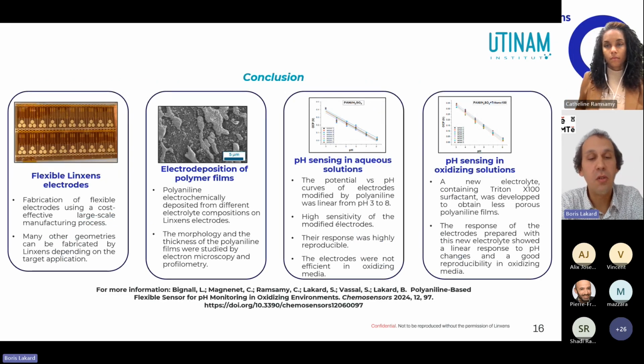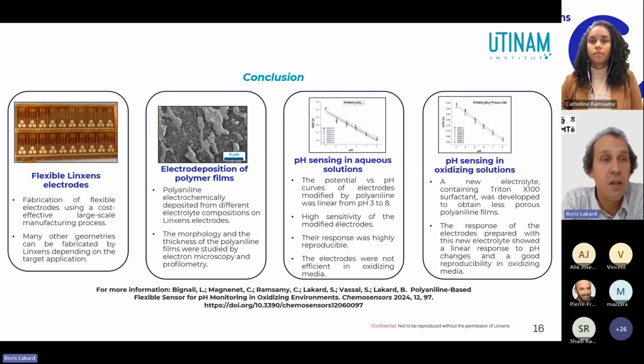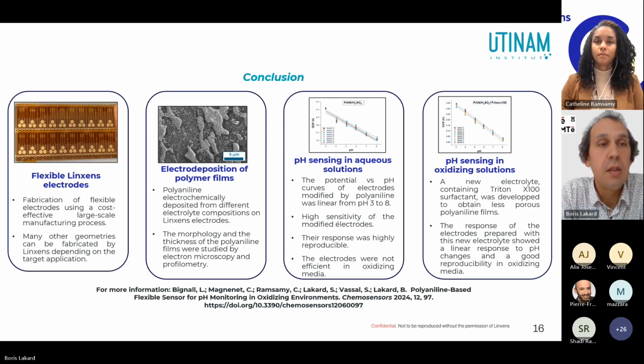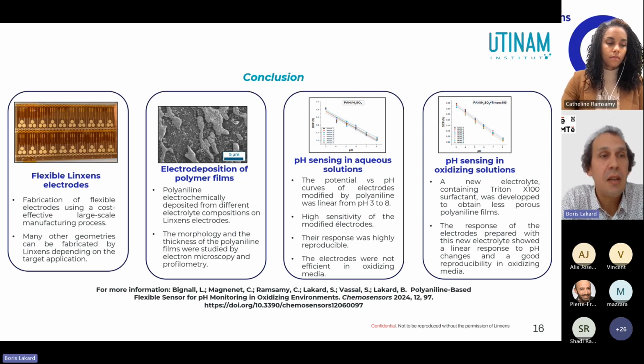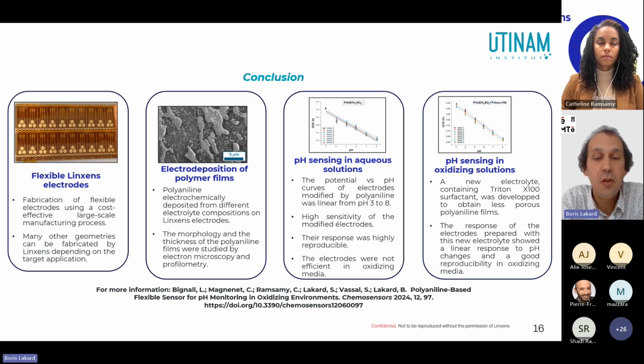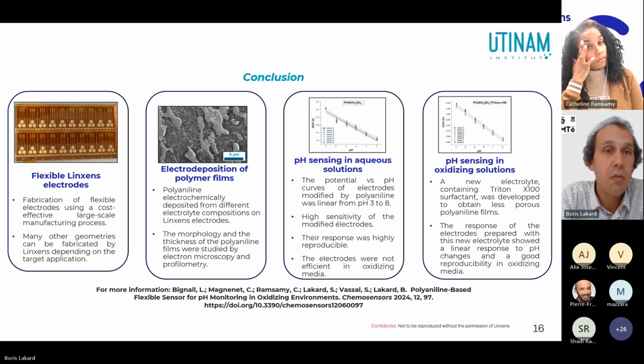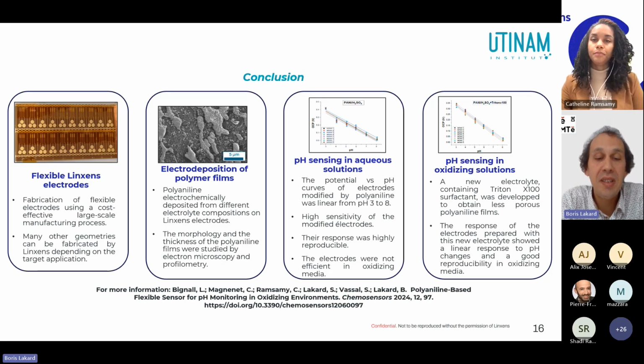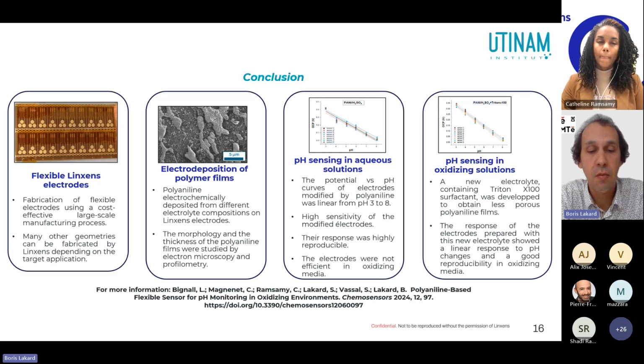To conclude, in this study, we used the Linxens electrodes as sensors. These electrodes are very interesting because they are flexible and the roll-to-roll process is very useful. Then we have covered the sensors with the polyaniline by electrodeposition. First, we have obtained excellent responses to pH changes in aqueous solution, which is the first interesting point. And after that, we have modified the composition of the film, and we obtained very good results, even in the presence of hypochlorite ions, so in harsh conditions.